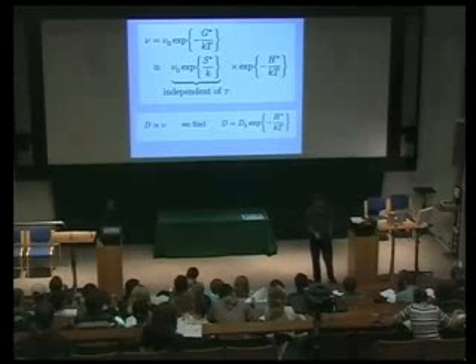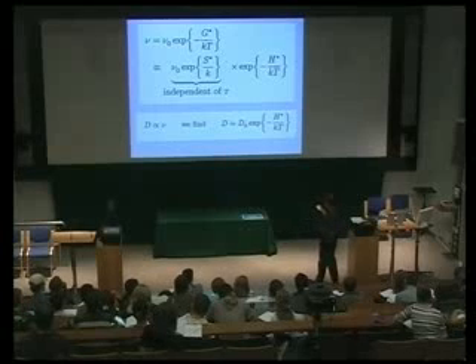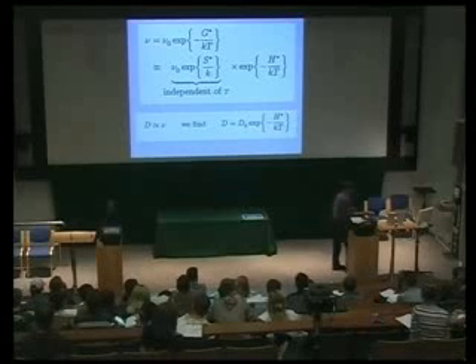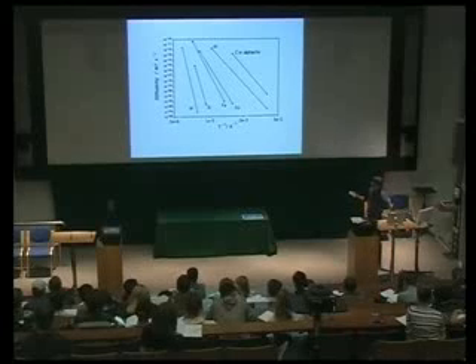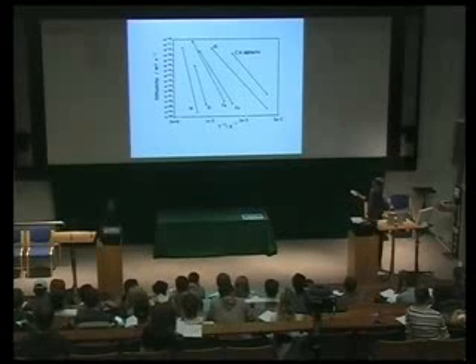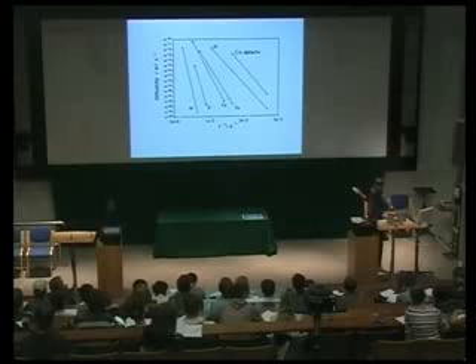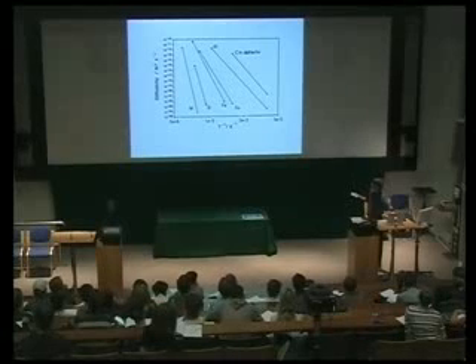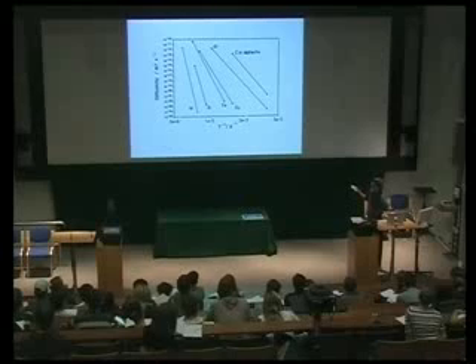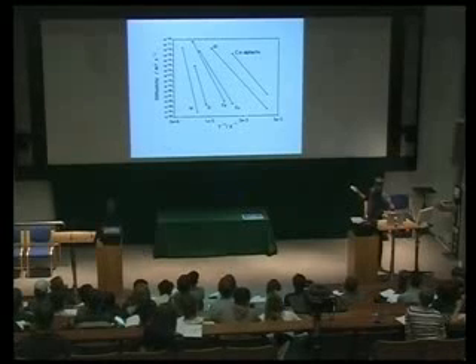There is a temperature independent term and an activation energy term. If I take the logarithm of the diffusion coefficient, then I will get a straight line if I plot against 1 upon the temperature. And here are some plots. So this is the logarithm of the diffusion coefficient versus the reciprocal of the temperature, and you can see straight lines. Now notice that the interstitial diffusion coefficient is very, very much larger than that of substitutional atoms. Remember, this is 1 upon the temperature, so low temperatures correspond to high values here. And you can see that at any temperature, interstitial diffusion is much faster than substitutional diffusion.